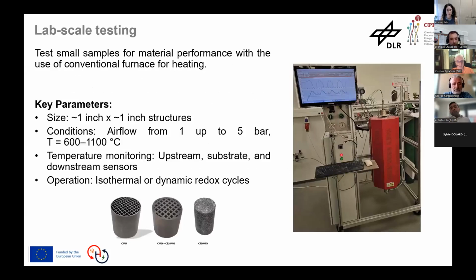In the lab, we test small structures around 1 inch in size under realistic conditions. These samples are heated in a conventional furnace and exposed to airflow pressures between 1 to 5 bar and temperatures ranging from 600 to 1100 degrees Celsius. We monitor the temperature at 3 points: the flow inlet, the substrate, and the flow outlet. The redox cycles may be isothermal or dynamic, depending on the test. This setup helps us evaluate material behavior and performance under conditions that simulate real-world industrial heat systems.